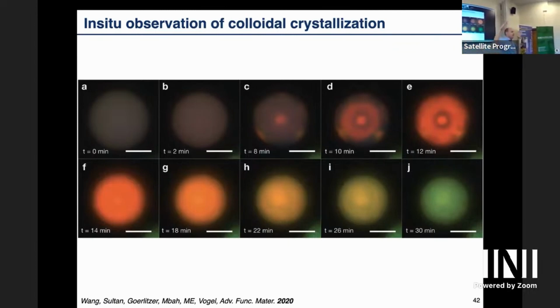So again, it starts ordering from the outside, grows to the inside, melts on the outside, and you have a crystal floating in a thin layer of liquid at the end. And then as we go on waiting longer, the crystal slowly gets compressed further and further. The lattice constant shrinks, so the color shifts towards smaller wavelength, and we see the color change in the experiment.